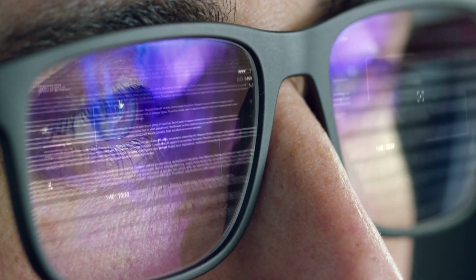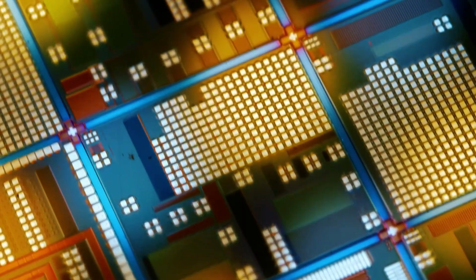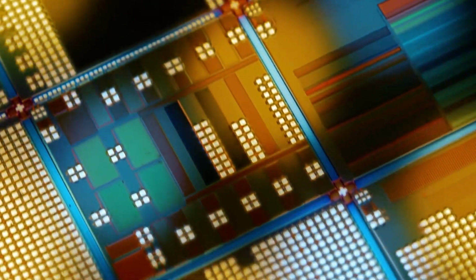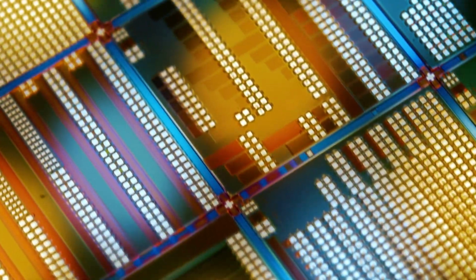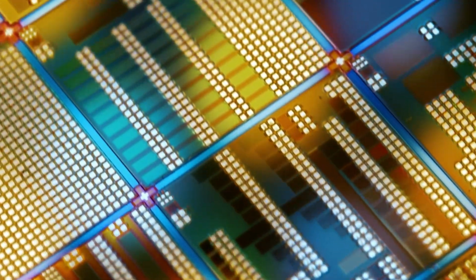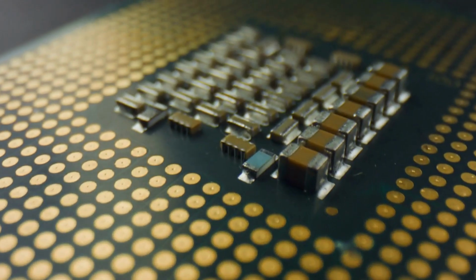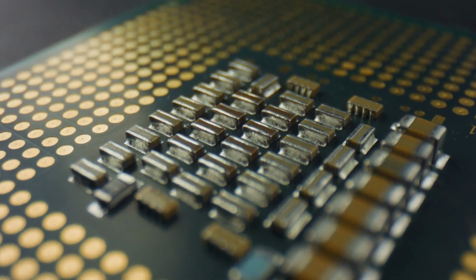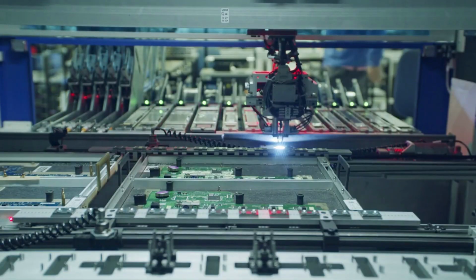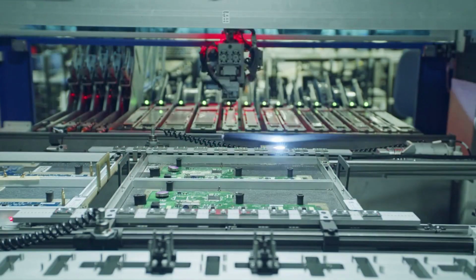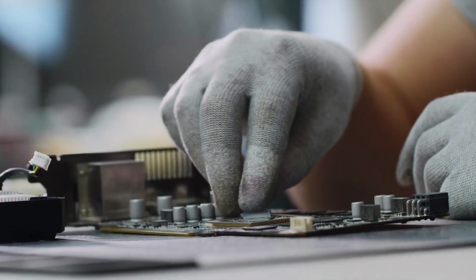The two surfaces being joined must be flat to within a fraction of a nanometer, not a few nanometers, a fraction of one, across a wafer that is 12 inches wide. And the alignment between the two surfaces must hold to sub-micron tolerances at every point across that entire 12-inch span. The error budget does not accumulate graciously. One misaligned micron, repeated across thousands of bonding sites, and the bond breaks down.